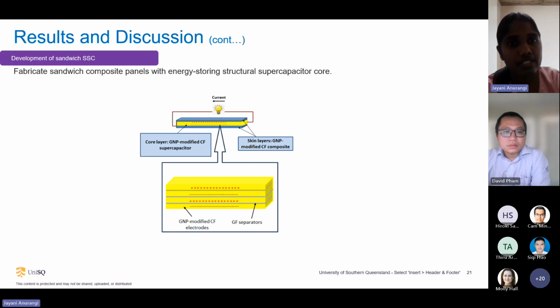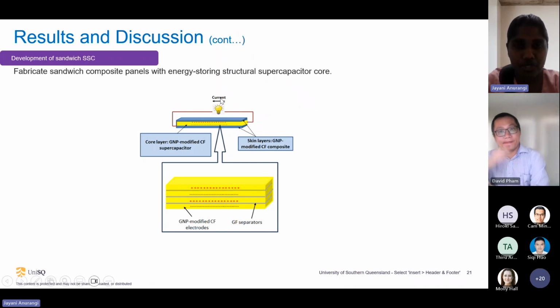After developing the skin layer and the core layer, my next objective was to fabricate a sandwich composite panel with an energy storing structural supercapacitor core. As shown in this figure, I prepared my sandwich composite. The layers were bonded by using two-part structural epoxy. This sandwich composite was fabricated by using the hot pressing method.